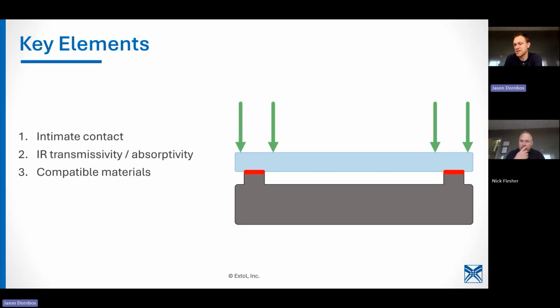So the answer to your question, I believe carbon black additive is one thing that prohibits transmissivity. Absolutely. Yep. However, it actually really helps with the absorptivity. You got to have some level of absorptive content, and carbon black is typically the cheapest. Fillers are bad. Fillers, inconsistent fillers especially, are bad.